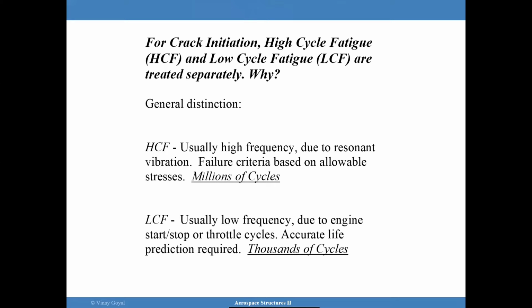So for crack initiation, high cycle fatigue and low cycle fatigue are treated separately. And the question is why? The general distinction is that usually with high cycle fatigue, you're looking at failing in the millions of cycles, and the failure criteria is typically based on an allowable stress. In some applications, strains can also be used as long as you have the data to support it. High cycle fatigue usually occurs when you have low amplitude loading and you're not going into the yield regime, but the loading is high frequency. An example of that could be resonant vibration most of the time.